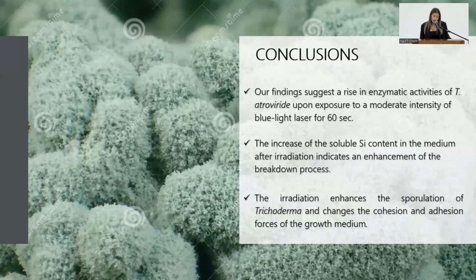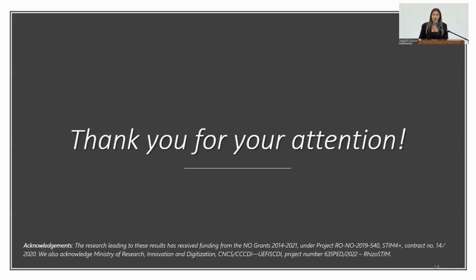In conclusion, our findings suggest a rise in enzymatic activities of Trichoderma atroviride upon exposure to a moderate intensity of blue laser light for 60 seconds. The increase of soluble silica content in the medium after irradiation indicates an enhancement of the breakdown process. And the irradiation enhances the sporulation of Trichoderma and changes the cohesion and adhesion forces of the growth medium. And thank you for your attention.